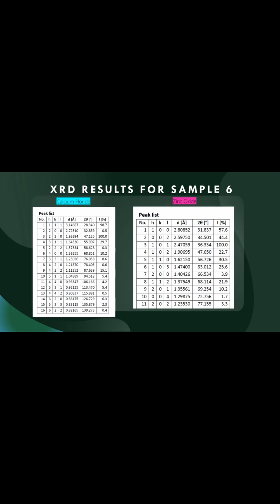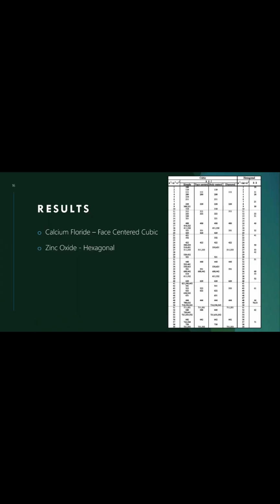Again, these are the respective peak lists for sample 6 as well as the HKL values. And this graph here shows sample 6 and sample 2. It does include sample 4, however, sample 4 was removed because of its similarity to sample 2. From the results, we can see that calcium fluoride is face-centered cubic and zinc oxide is hexagonal. And using the Miller indices, we were able to look at their HKL values to determine this.